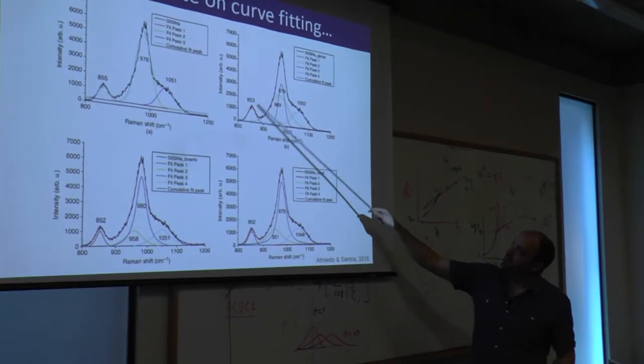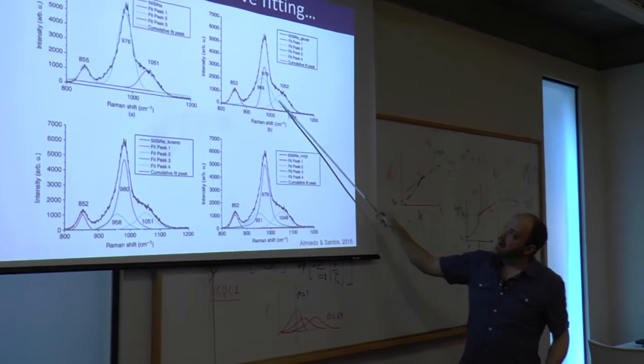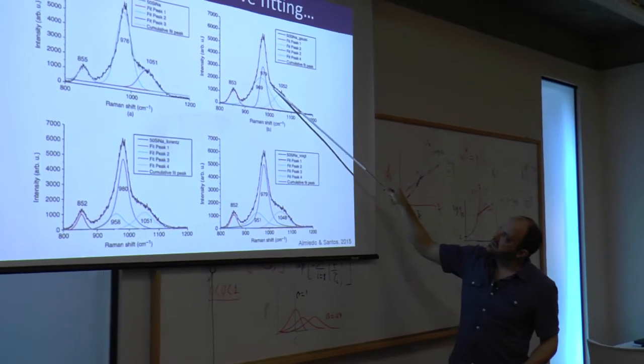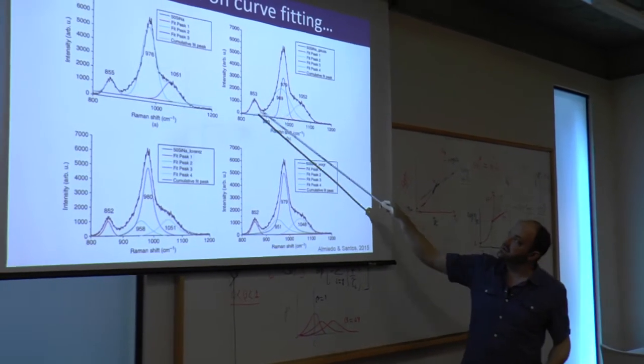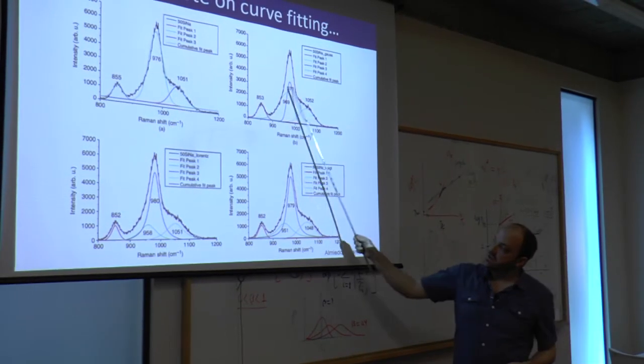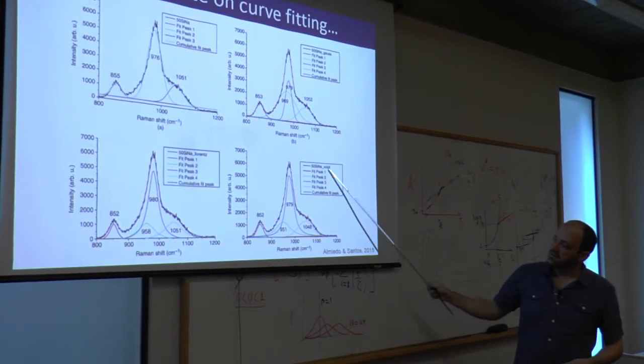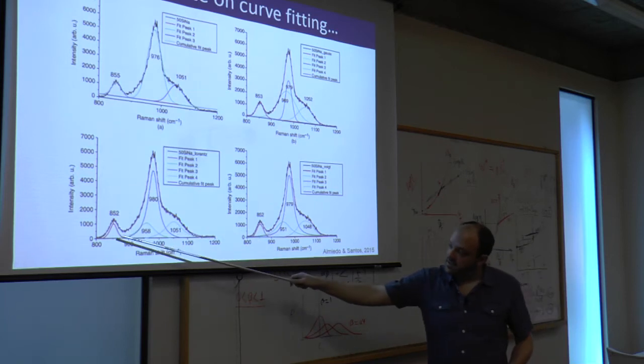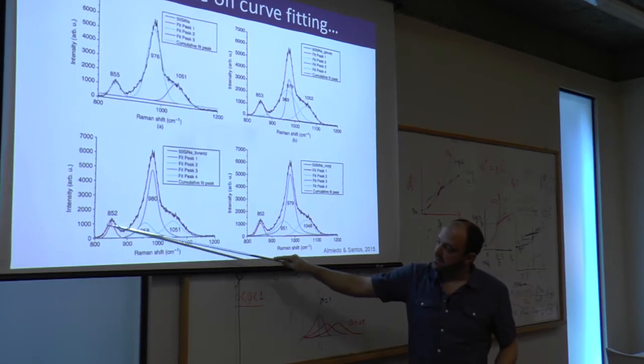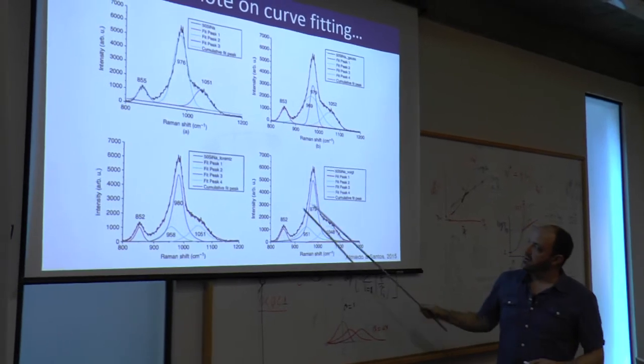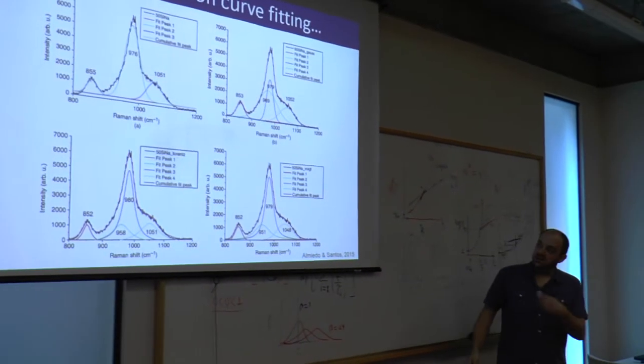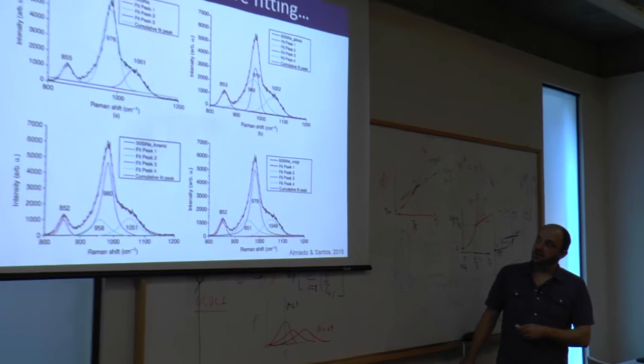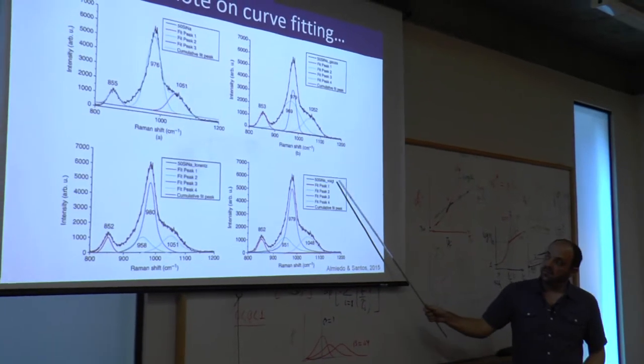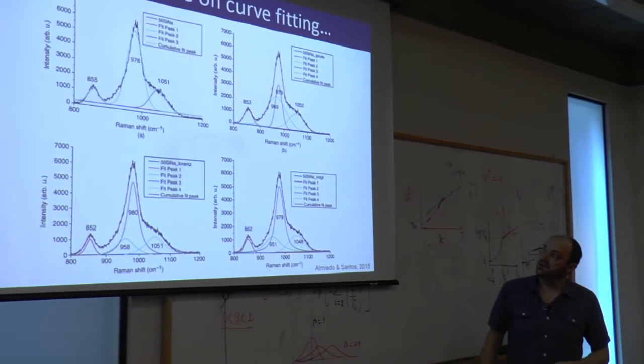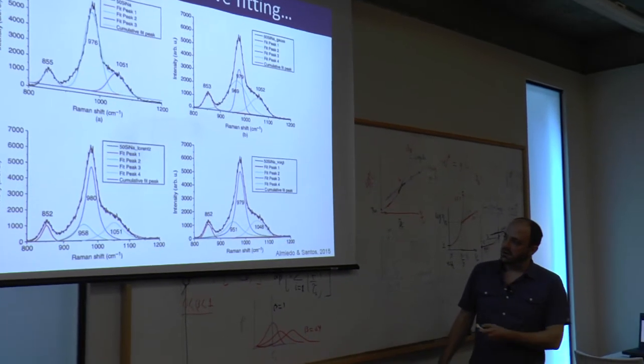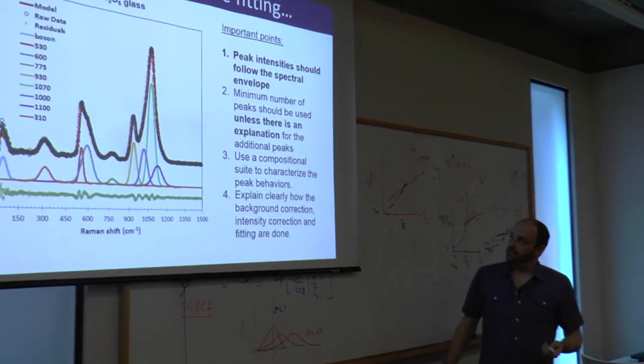So here is 4 peaks. This one is not too bad. You can see the model generally fits. There's a slight mismatch here, but generally it fits the overall spectra shape. If you change the shape of the curve to Lorentzian or Voigt and use the same 4 peaks, we can see that you start to get some mismatch with other peak shapes. And that's the same as we saw in the last pane, where using different Voigt and Lorentzian peak shapes doesn't really work so well for glasses, in my opinion.